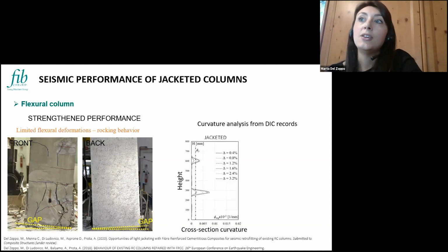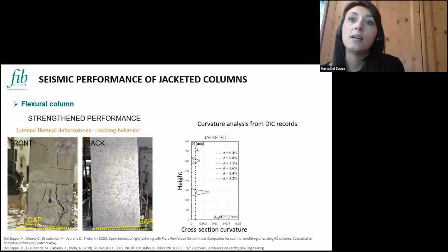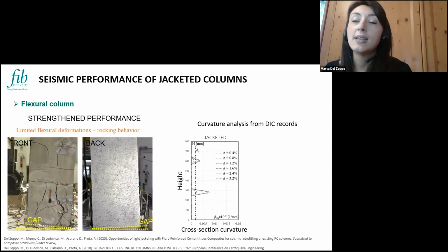To further understand the overall performance of the jacketed columns, we performed a curvature analysis starting from the DIC records. Basically, the digital image correlation is able to provide a picture of the strain over the surface of the element at each instant of time. From these strain values, we can define the cross-section curvatures at any step of the test, and then define how these cross-section curvatures are changing over the length of the specimen for each imposed displacement or drift.